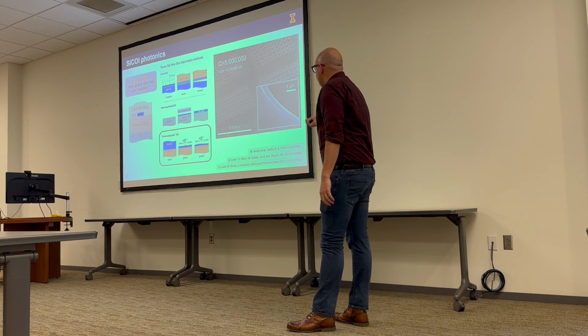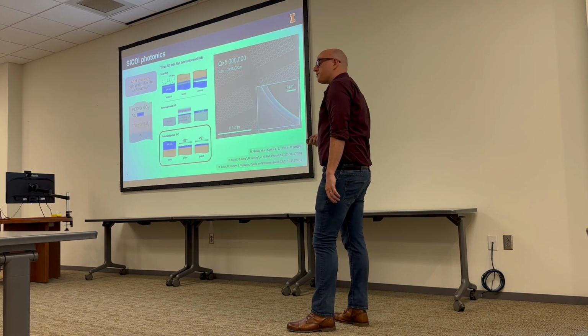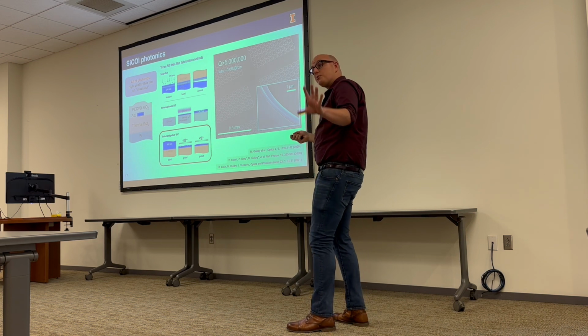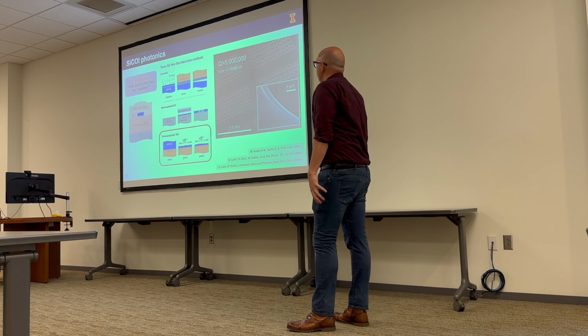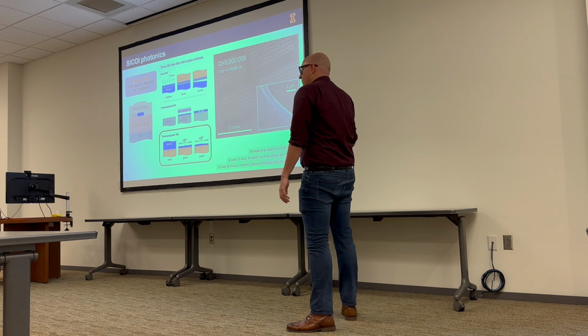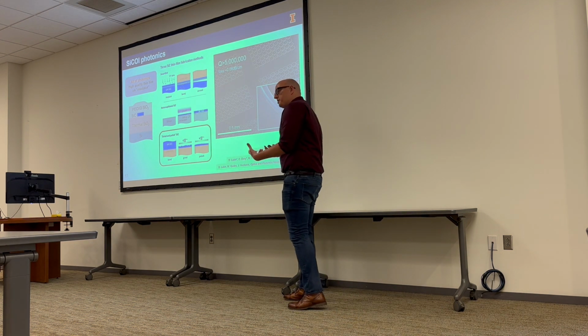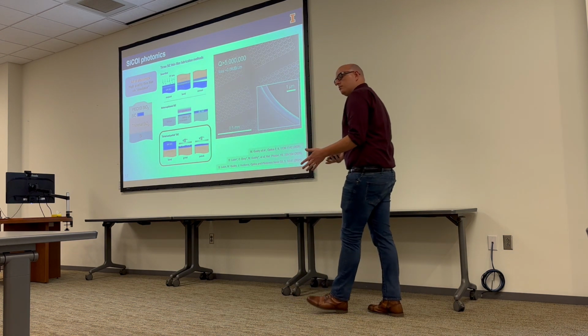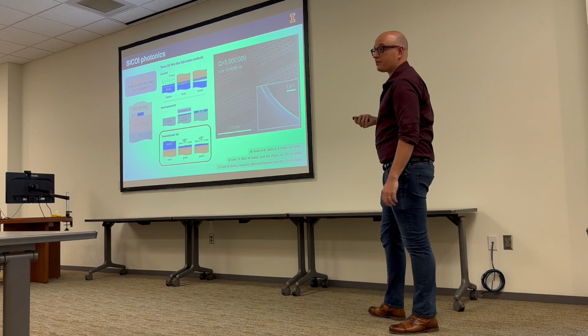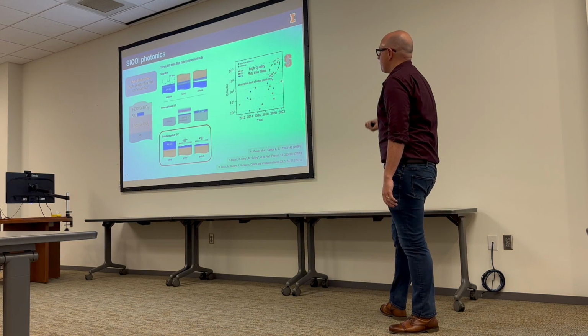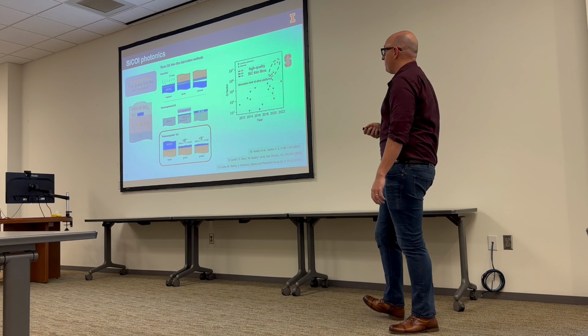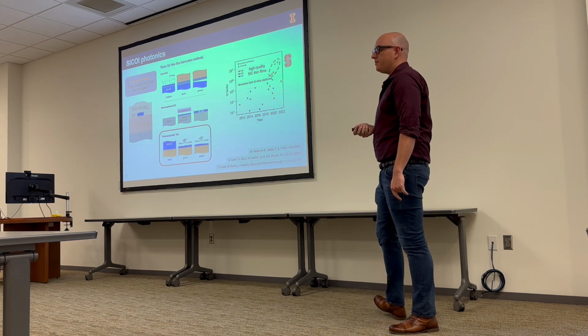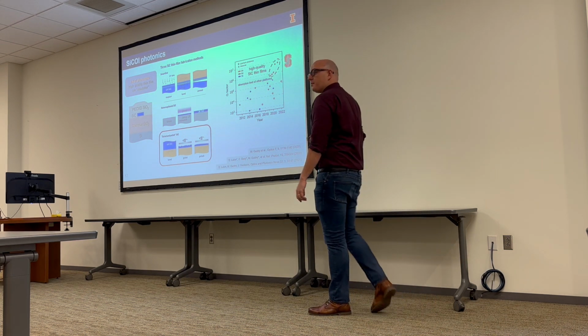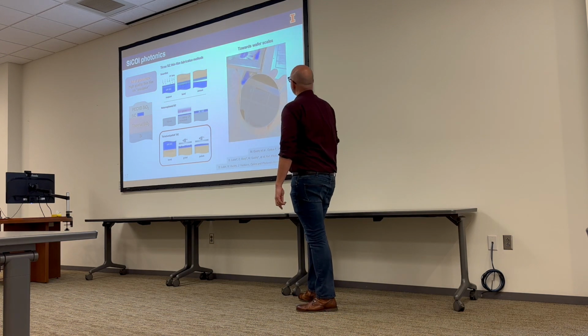So here are some ring resonators where the light is circulating in this ring. The etches look great, which is a big plus for us, especially over diamond. The losses are very low and the quality factors can be quite high. So we have this ability to make high Q, low mode volume, integrated photonics, all in silicon carbide. And over the past few years, we've really been boosting up the quality factors in the system to almost 10 million, which we're excited about.